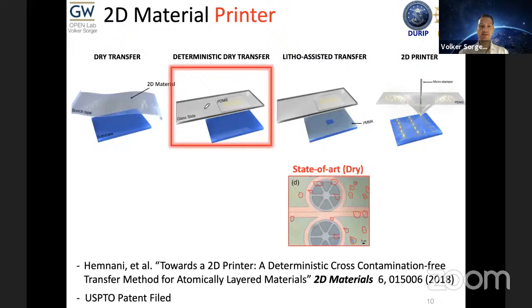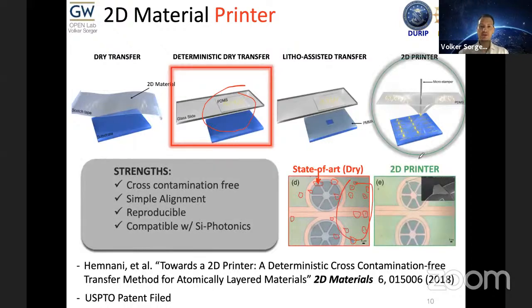So typical systems use a flat structure when you transfer them, let's say on a photonic chip, for example. So yes, you get this particular flake here on this ring resonator, but you also get a lot of other parts that you don't like. Now, what we can do is use this microstamper approach on the right here, and we can very uniquely transfer only one material without cross-contamination. So here is a little video that shows this.